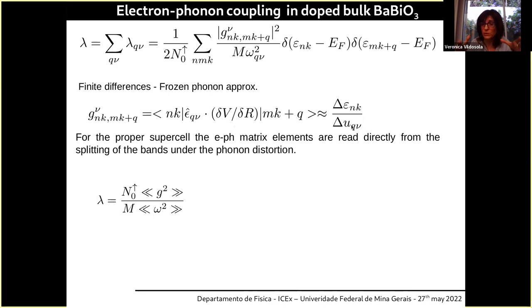So if you do a proper supercell calculation, you shift the ions from the equilibrium position according to a given collective mode, and you measure this matrix element with the shift of the electronic levels. And you can estimate this number with this very complicated double summation. It's very unstable, it demands very dense coupling meshes because of these two deltas. And also you have to calculate the phonon frequencies of these collective modes.